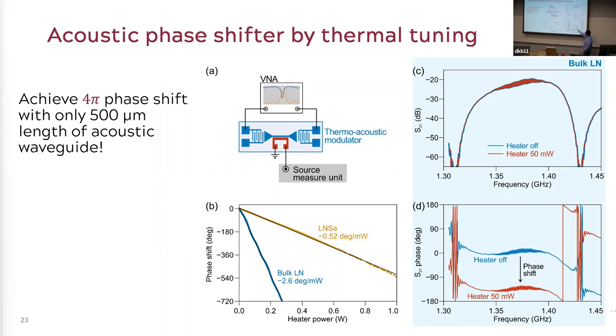If I turn the heater on and off, the amplitude does not change. So it's not an amplitude modulation, it's a phase modulation. The amplitude does not change, but you can see the microwave phase gets shifted by almost 90 degrees by heating with only 50 milliwatts. Yeah. So this is very useful for microwave signal processing, where you need something to be very stable. Usually those thermal effects are relatively more stable than the electrical control approaches.